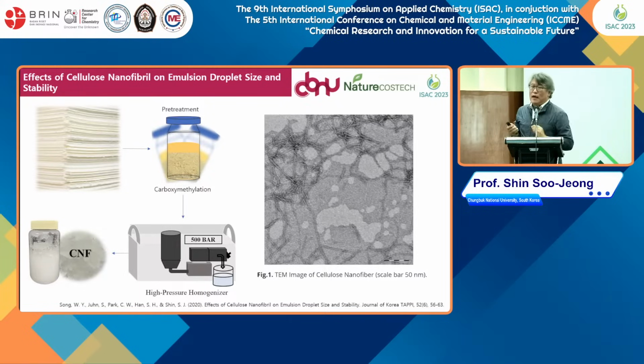When we make an emulsion, cellulose nanofibrils work as a networking structure that improves emulsion dispersing property. We made an oil and water emulsion, added extra cellulose nanofibril, combined it by homogenization, and checked emulsion stability. Putting in cellulose nanofibril improved emulsion stability a lot, preventing phase separation of the oil phase and water phase.